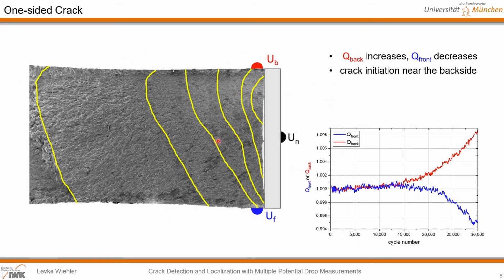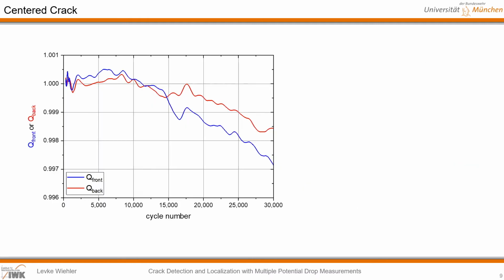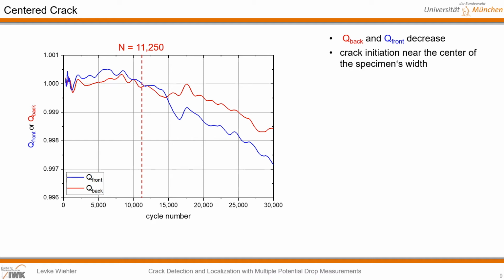The fracture surface of specimen 1 shows a fatigue crack emanating near the back side of the specimen. By counting back the overload marks, the crack initiation can be assigned to the first overload. Therefore, the detection and localization of the crack was after 15,000 cycles. In case of specimen 2, a crack can be recognized after 11,250 cycles. At this point, both quotients are decreasing and below the value 1. In this case, the potential U_n exceeds the other two potentials, indicating the initiation of a crack in the center of the notch.